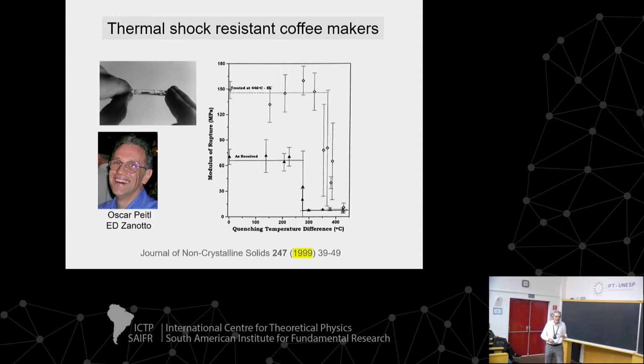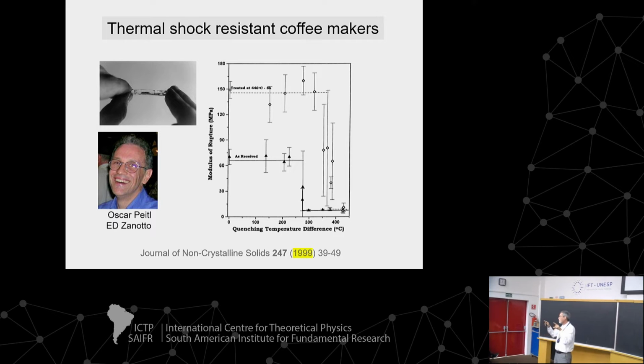And we had a demand from a company producing coffee makers. You know these glass coffee makers? They're very brittle. They're very fragile. It's easy to break them. So they wanted to improve their fracture strength and thermal shock resistance. So we used this process of chemical strengthening. And this is the fracture strength and the quenching difference. You quench the glass in a bath of ice and water and measure the strength again.